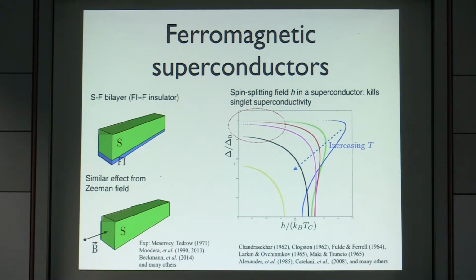What you get is something that was known already since the 1960s. You can study a superconductor in the presence of an exchange field. There are two ways to realize this: either a ferromagnetic insulator next to the superconductor inducing a magnetic proximity effect, which was also discussed yesterday by Jagadish Moodera, or the Zeeman effect of an applied magnetic field, which is in plane. What you get here is the superconducting gap versus the exchange field.